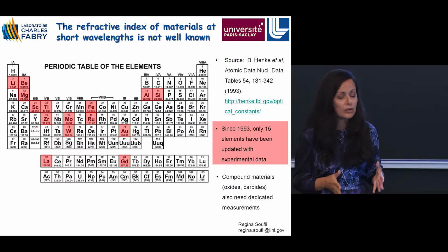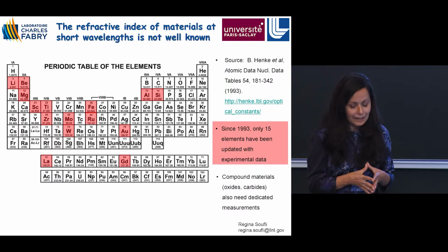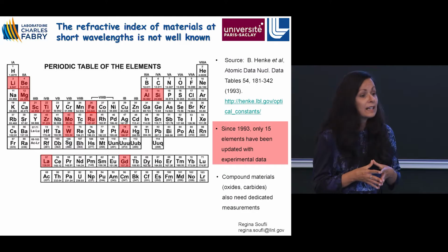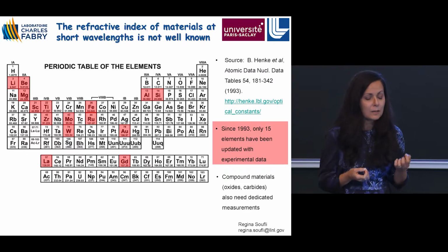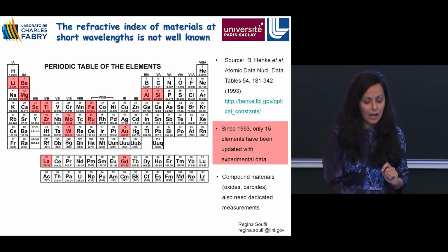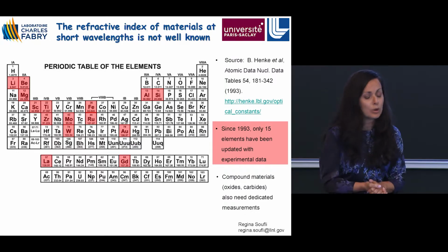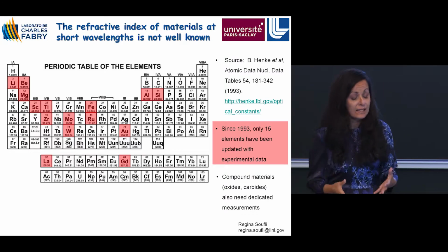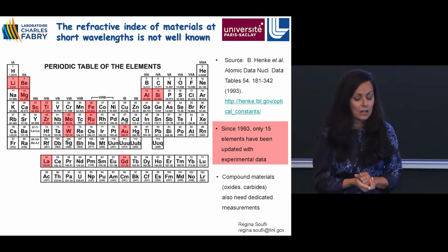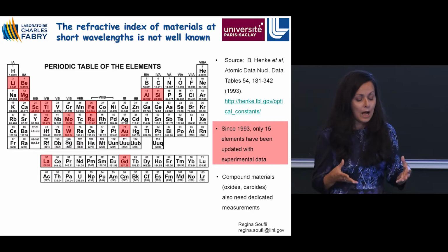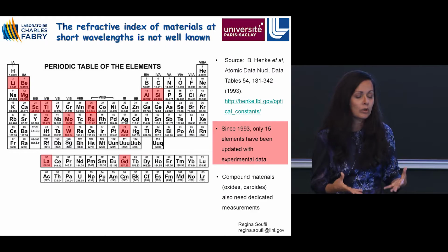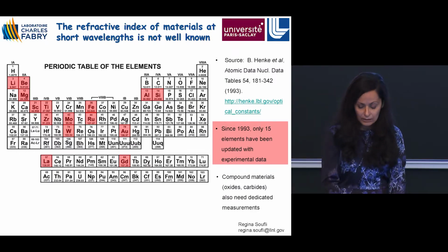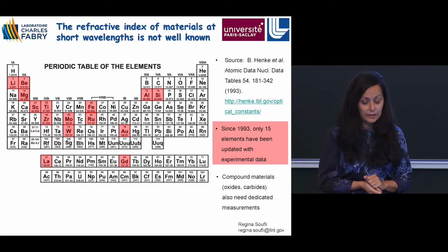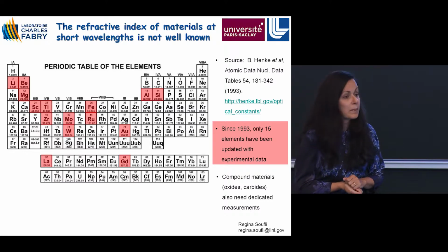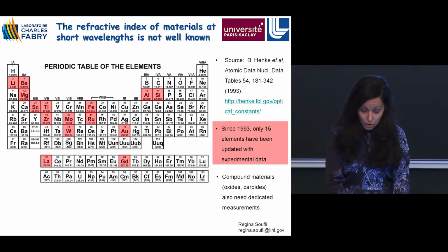It is a compilation of experimental data from the 1900s to about 1980, combined with theoretical calculations, which assume that matter behaves in an atomic-like manner. This assumption, as you know, is not true near absorption edges. And therefore, in the vicinity of those absorption edges, where you have interatomic effects, intraband transitions, and other chemical effects related to the chemical environment, you need to do experimental measurements in order to determine the refractive index of materials accurately. And it turns out that since 1993, only 15 elements have been updated with experimental data, which is not a lot.